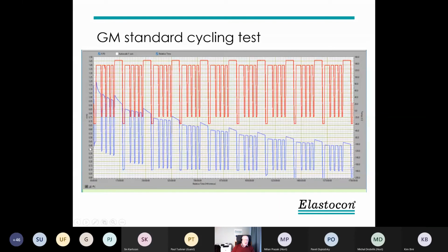The cycle starts at room temperature, and then we are at F over F0, 1. So we take a reading at room temperature here. Then we immediately go down to -40. Then we can see the effect of just the shrinkage. We have no aging done yet, just the shrinkage. Then we have a warm cycle, and then we go down again to -40 here. Here is -18. So compare that one with that one.